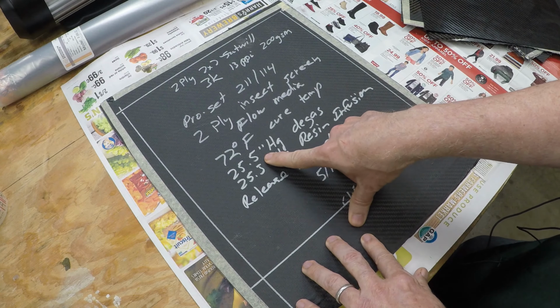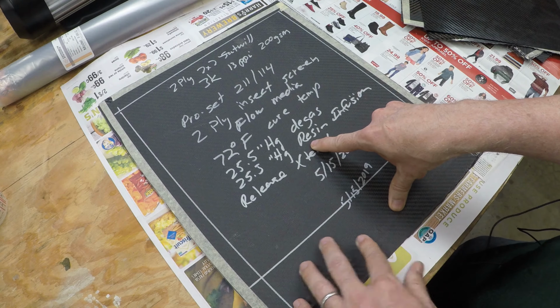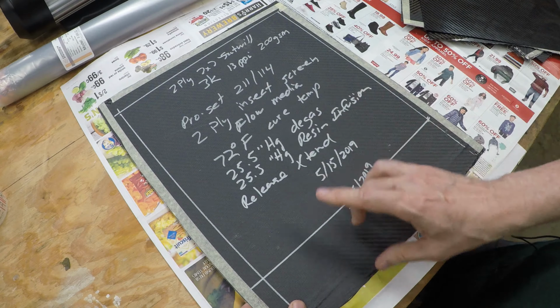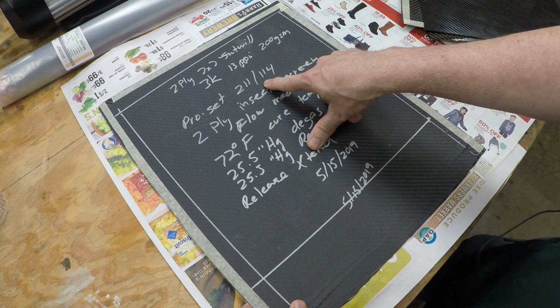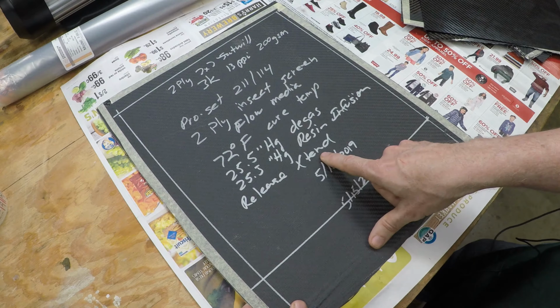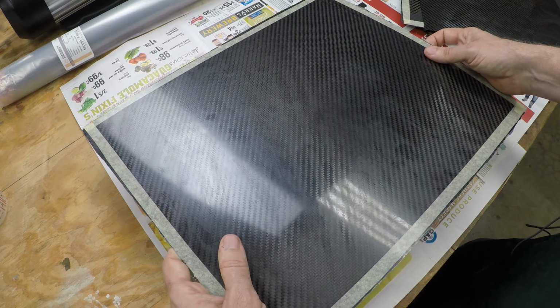So I degassed at 25.5, and then I ran the infusion at 25.5. And in this case, everything else is the same, so I used the Proset epoxy, and I used the Xtend release. In this case, the finish is good, but not as good. I was getting some very small pinholes. So you might be able to see there are some very small pinholes, but overall, it's still a pretty darn good finish. In a pinch, I could use that 25.5 inches of mercury pump, but I think I'll use the bigger vacuum pump from now on.